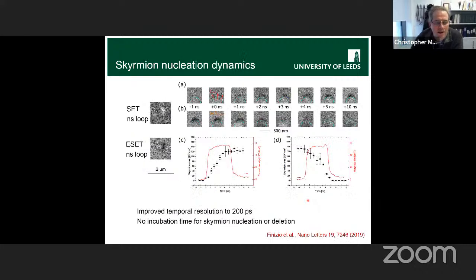And then we studied that at high speed as well, because they like to do magnetization dynamics on that microscope. There are little movies here, but maybe if you look at these snapshots, you can see zero is the start of the pulse, and this patch of dark contrast grows. And this row is annihilating it again with the field. This is the thing that's most interesting to me, and this graph shows you what's happening there as a time series.